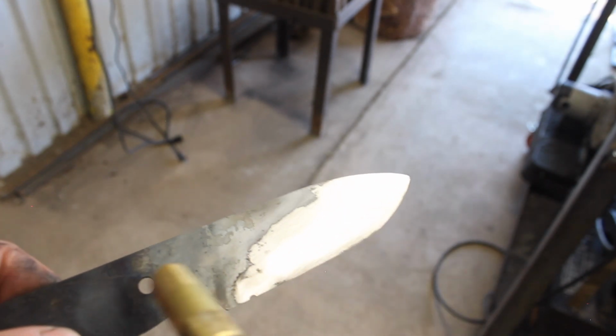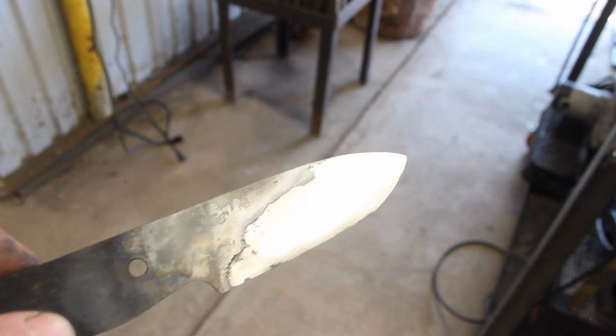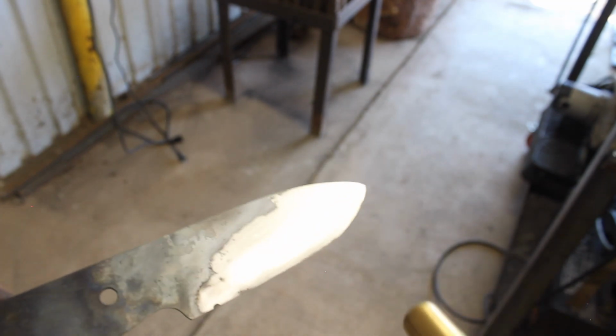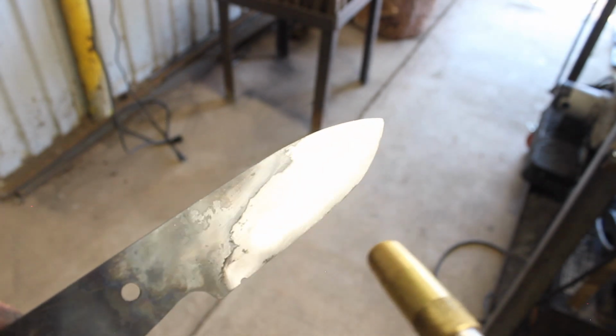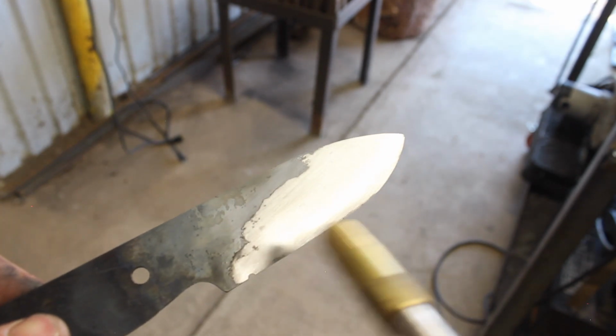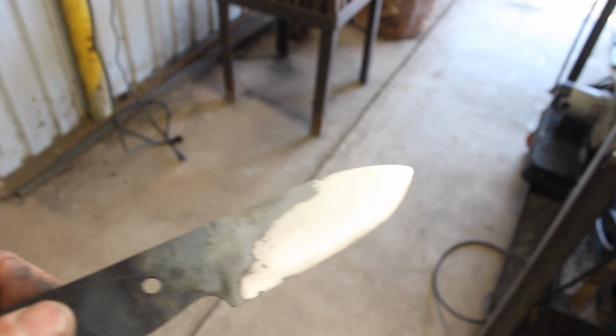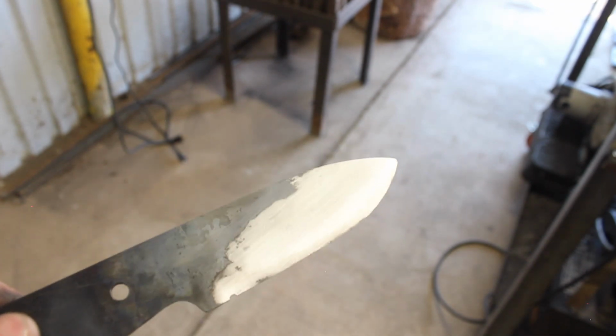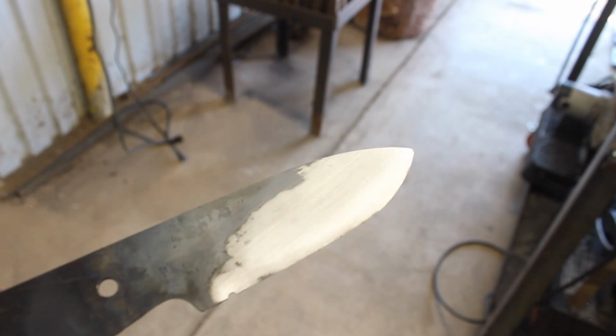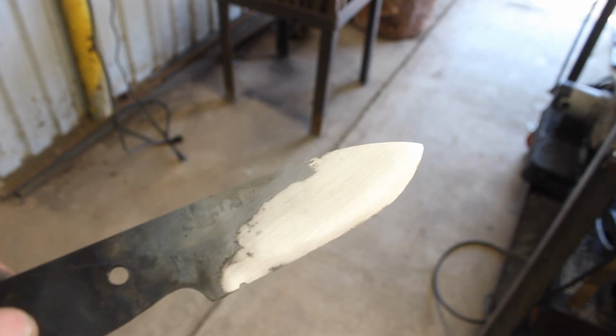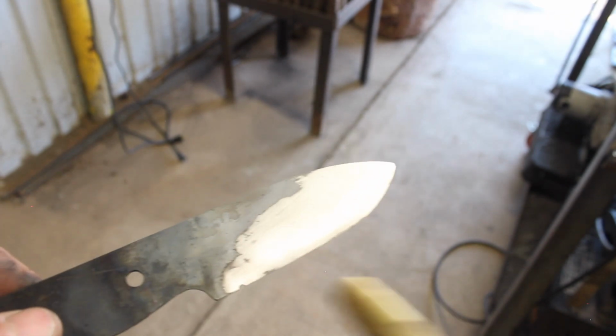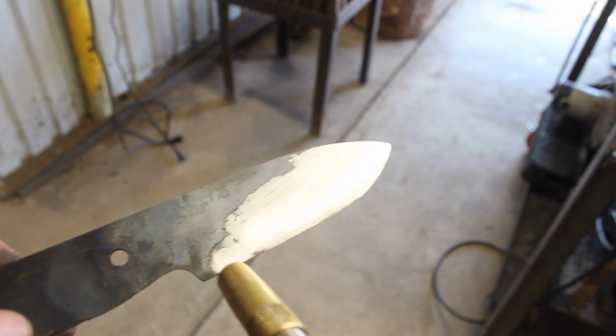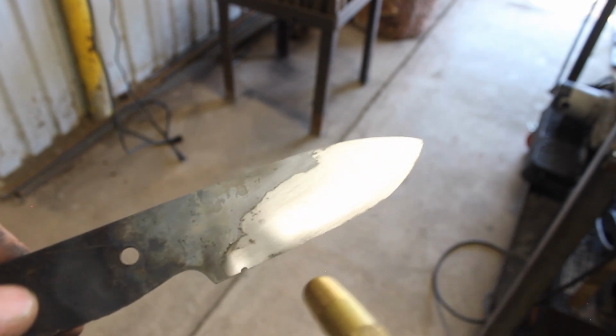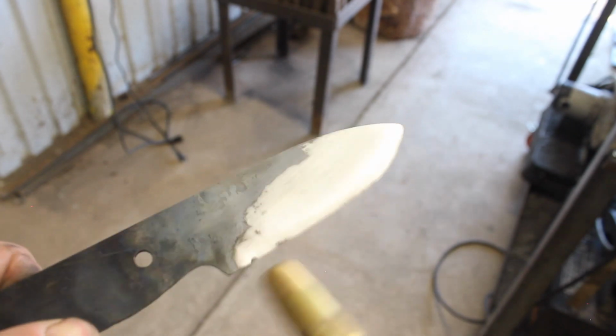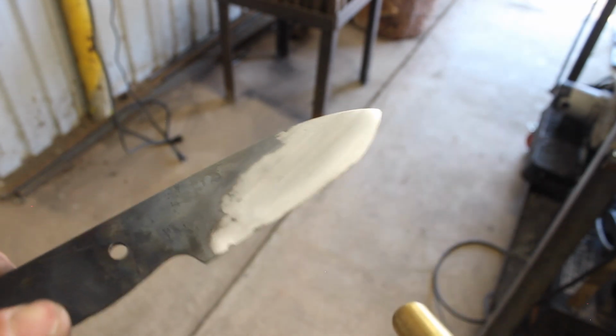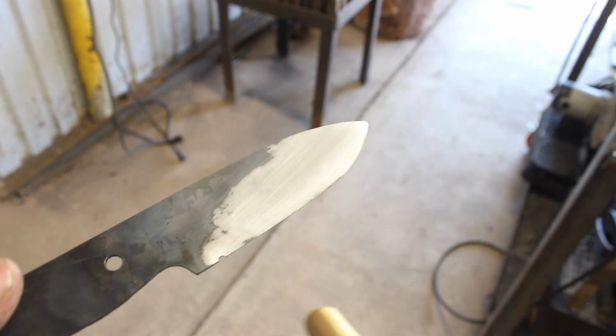Now this method where you watch your colors, the tempering colors run, you have to know approximately at least what the carbon content of your steel is in order for that to be of any use to you. You could temper a piece of steel out to say a light straw or a dark straw or a vermilion or a dark blue or whatever, but it really doesn't mean anything unless you know what the carbon content is. And since we know this is about 0.8% carbon, I'm going to go with a light straw that's going to give us a nice hardness to the edge so that we have a good edge holding capability on this knife.